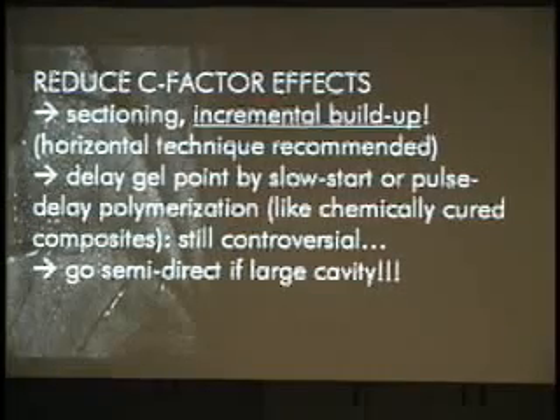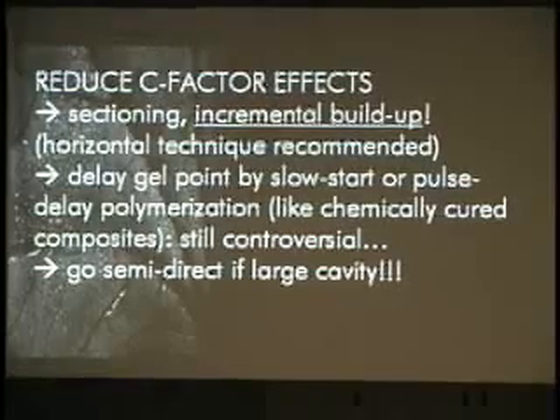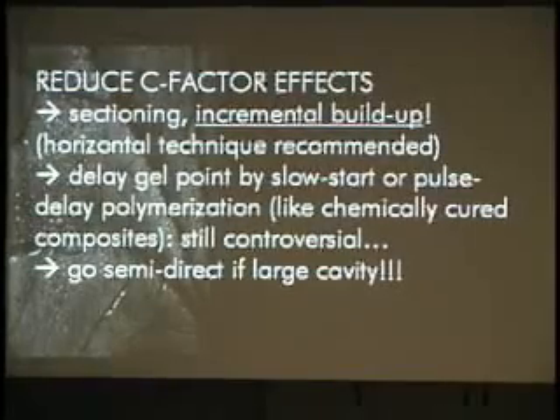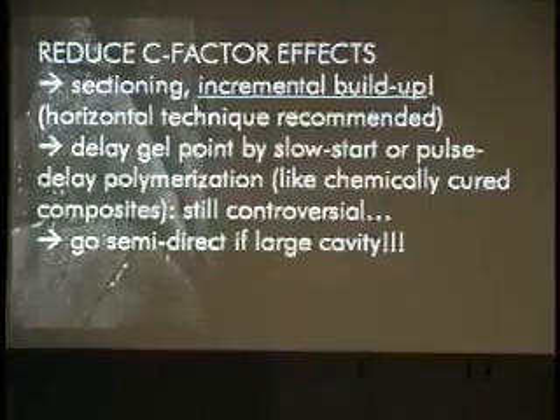So common sense is telling us that when we cure composite, the use of very highly powerful lights and very fast polymerization doesn't make sense in that concept. And that's why lots of techniques have been developed, like the slow start or pulse delay polymerization technique that uses very low intensity at the beginning and that raises at the end. Now, common sense is also telling you that if your cavity is too large, just go to the next step. Go for semi-direct or indirect.